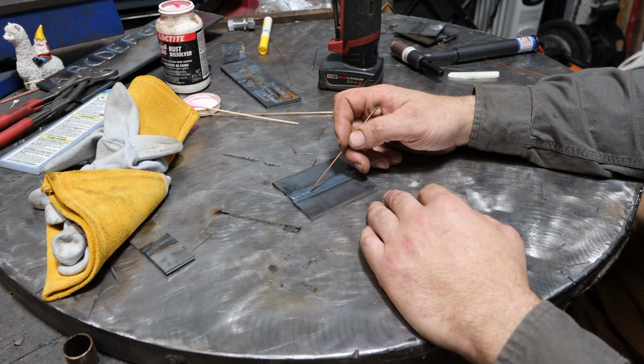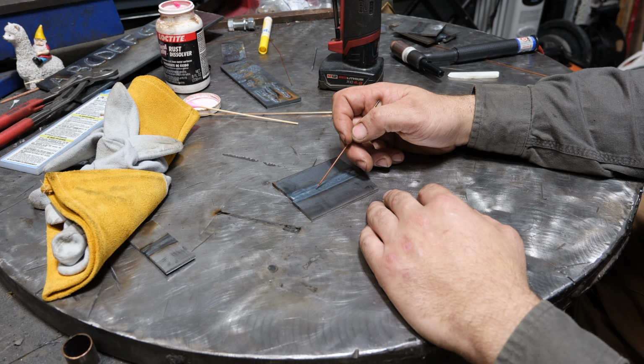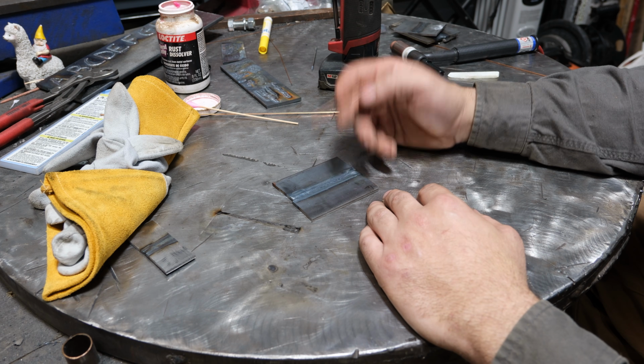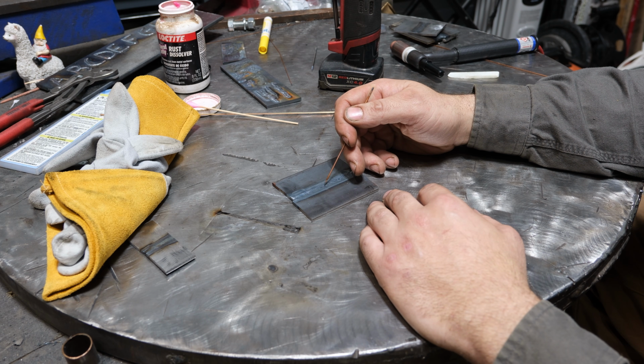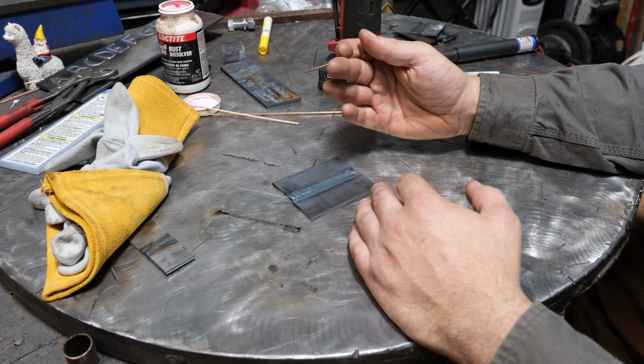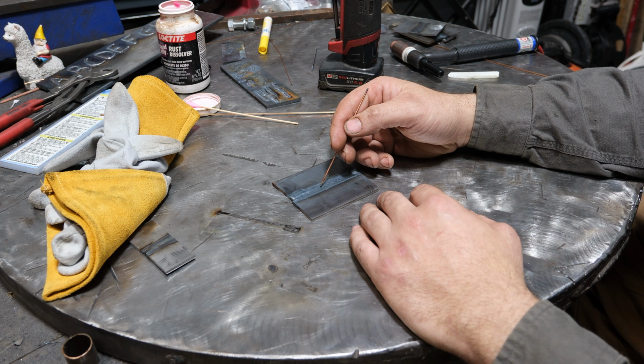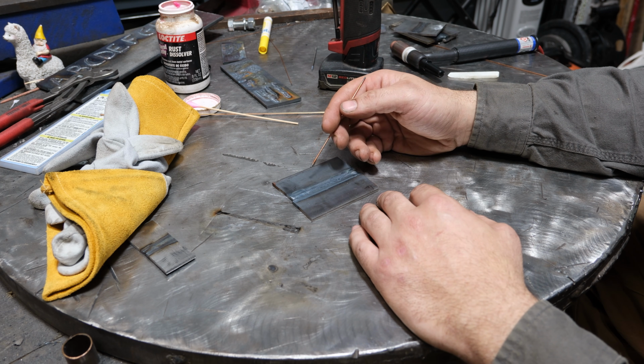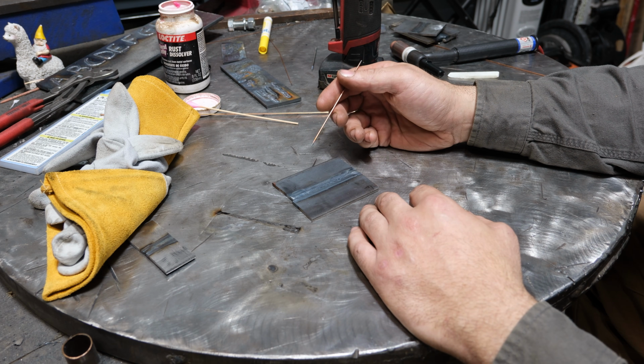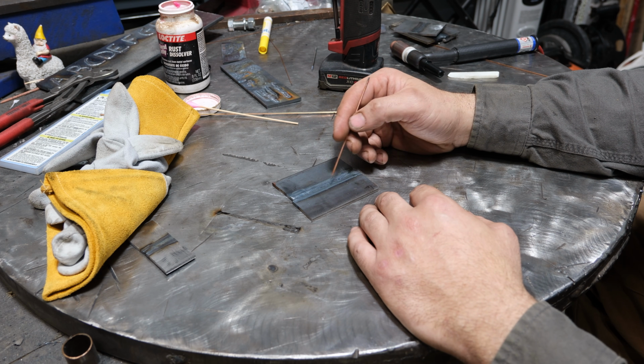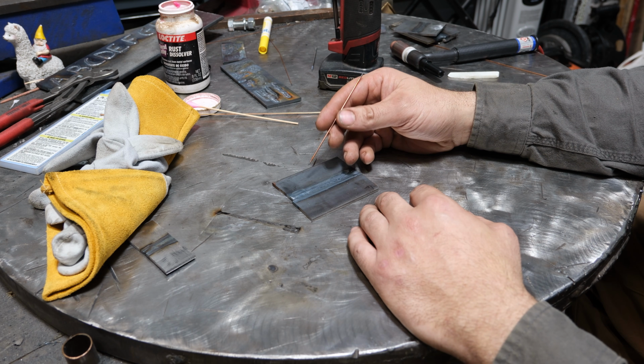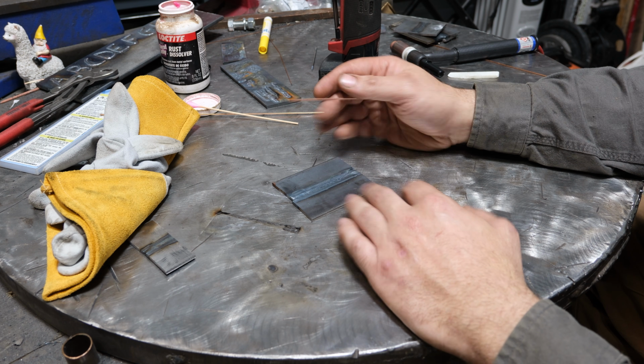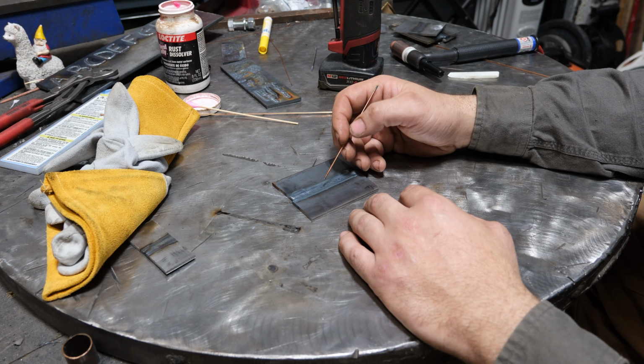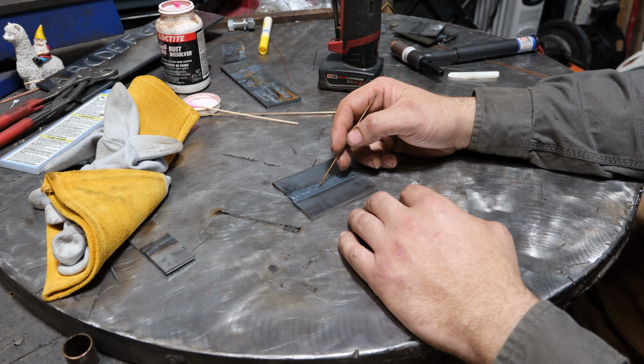that is if you're feeding filler and you notice that the rod is sticking to the plate, you may be hitting too far forward of the leading edge, or when you retract it out of the puddle, you're touching it to the plate, or you're just running too low of amperage. And it's a good indication if the filler rod's sticking, you're not running enough amperage. If you increase the amperage and the filler rod doesn't stick but you're melting through the plates, well then you probably need to go down in filler rod diameter to make that all easier for you. So you want to be mindful of running enough amperage.